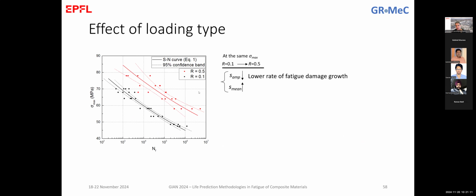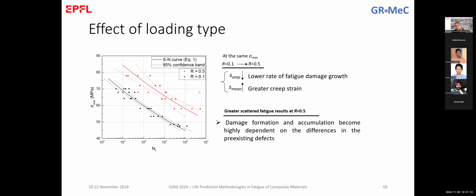Another part of the investigation was the investigation of the loading type. We did two different loads. Both of them are tensile, so we didn't go to compressive loading there to avoid any problems of buckling, and we didn't want to use any anti-buckling devices. And there we've seen that the scatter was more at 0.5 compared to 0.1.